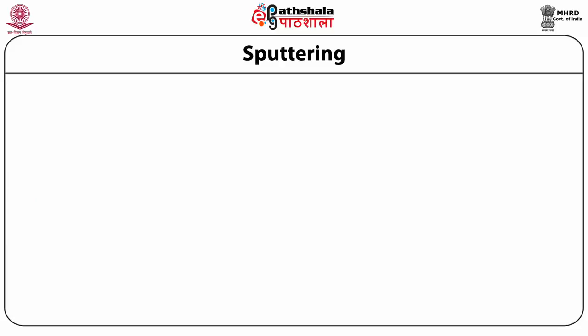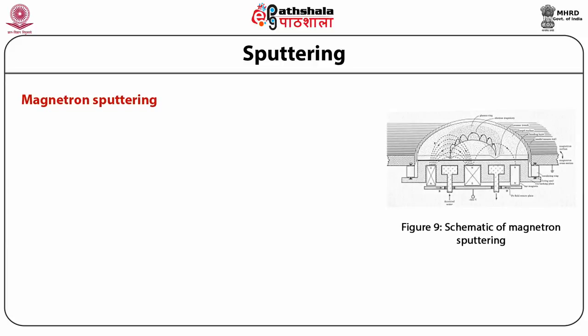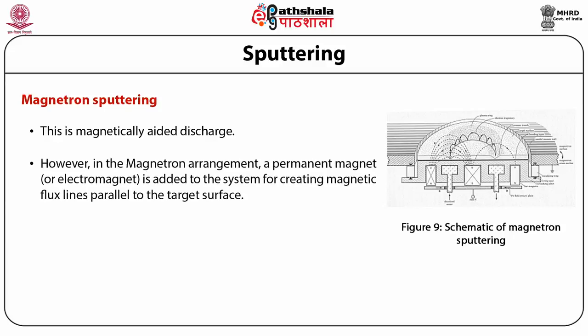So the last type of sputtering is magnetron sputtering, and this figure shows the schematic of magnetron sputtering. This is magnetically aided discharge. As we know, in DC and RF sputtering, the electric field is perpendicular to the target surface. However, in the magnetron arrangement, a permanent magnet or electromagnet is added to the system for creating magnetic flux lines parallel to the target surface.